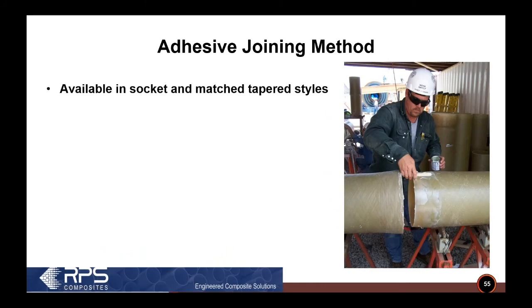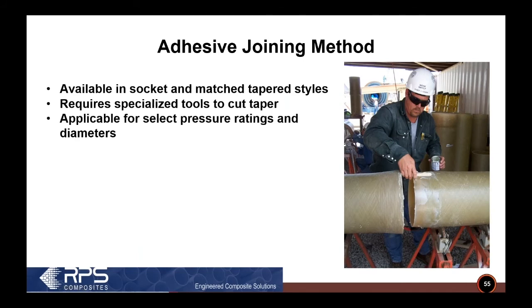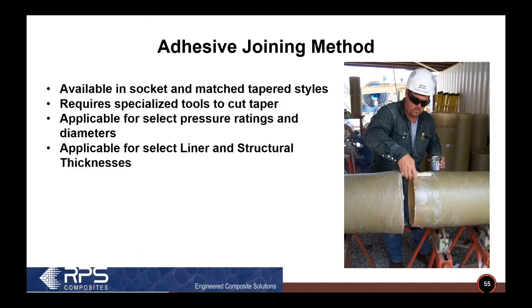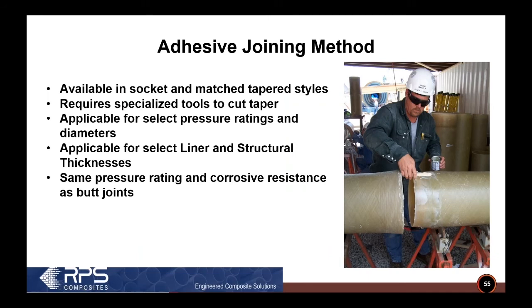So in our system, we have a socket and we have a matched taper on both the female and male ends. It does require a specialized tool to cut the taper, and it's really only applicable to certain pressure ratings and diameters and liner thicknesses and structural thicknesses. That's because the geometry has to be maintained to make the joint work. It has the same pressure rating though, the same strength essentially as the butt joint.